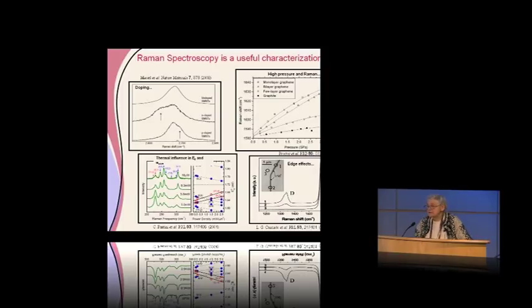These frequencies, you change the separation by a little bit of the carbon-carbon distance, not very much is necessary, and you get big changes that you could see in the spectrum. So temperature-dependent phenomena could be measured. You could measure equilibrium or lack of equilibrium between electrons and holes, because you could probe the phonons and probe the electrons at the same time. The electrons come in terms of the wave vectors that are chosen, and the phonons come in by the phonon frequency. So on this very same shot, you can study electron-phonon interaction in this kind of way.